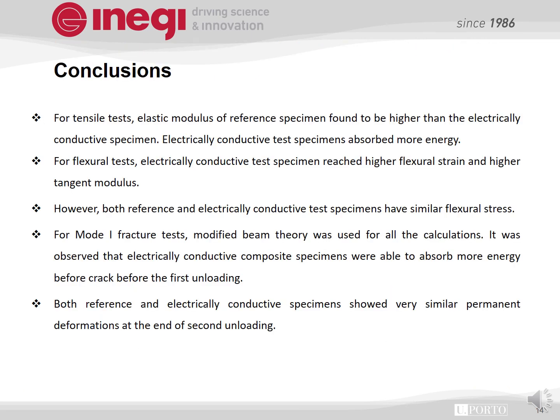Conclusions: for the tensile test, the elastic modulus of the reference specimen was found to be higher than the electrically conductive specimen. Both the specimens reached identical maximum stress, but the electrically conductive test specimen absorbed more energy, as we saw from the maximum strain, since the electrically conductive specimen can reach higher values of strain. Thus, these electrically conductive specimens have higher toughness than the reference specimen. For the flexural test, the electrically conductive test specimen reached higher flexural strain and higher tangent modulus as compared to the reference specimen, but both have similar flexural stress.